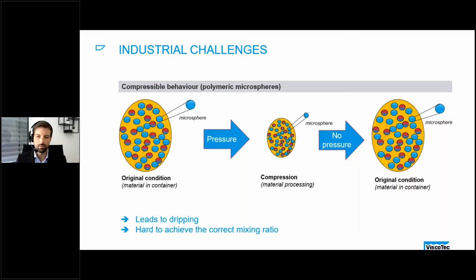Now I would like to put a deeper focus on the compressible behavior of such polymeric microspheres. And this is absolutely the industrial challenge. If you have the material in the original condition, in the original container, for instance in the cartridge, we have a certain volume of the material. But once we put pressure on the material, and even our systems are quite low pressure systems, the material gets compressed in the end.